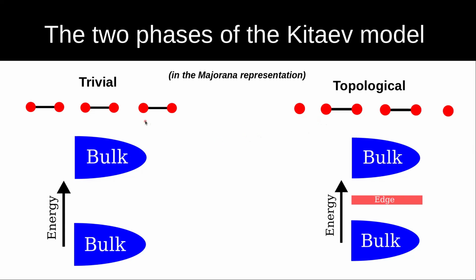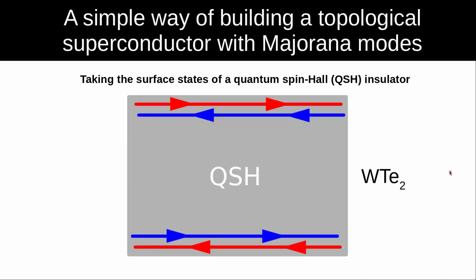And then, of course, the model also has a trivial phase, which appears when your chemical potential is much, much bigger than any other energy scale. And in this trivial case, essentially each Majorana mode is coupled within each site. So you can think that this is the limit where your Majorana modes are confined and they form a single electron. And this is the limit where one of the Majoranas is deconfined, in particular for the site at the beginning and the site at the end. And of course, in this topological case, we get an edge mode that is a topological state that is our Majorana zero mode.